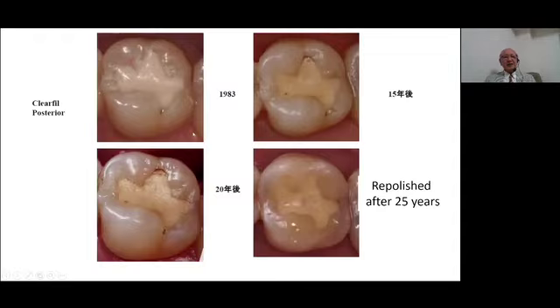This is one of his clinical cases. This is immediately after the restoration. It was in 1983. After 15 years, you can see some slight marginal discoloration and surface porosity, because the composite resin had to be mixed together, because it was the chemical cure type, not the light cure type composite. And this is after 20 years. Still okay. And after 25 years, the surface was repolished. By repolishing or refurbishing, this old restoration can be renewed like this. Again, we can expect another 25 years of clinical performance.